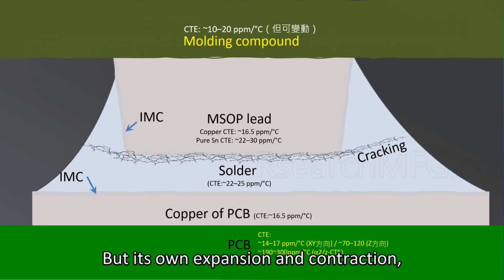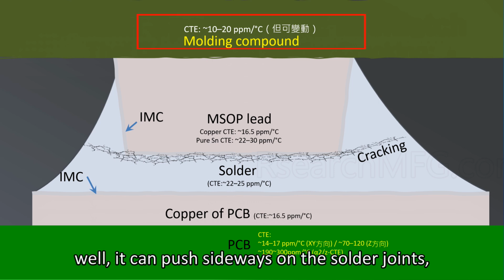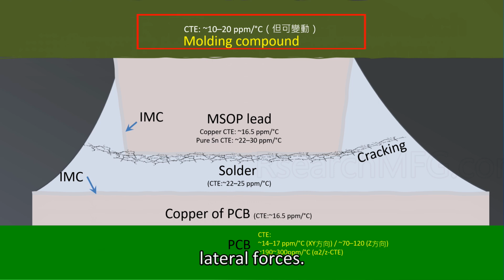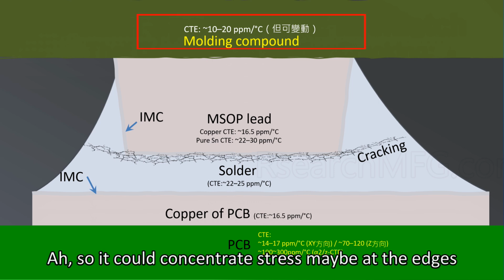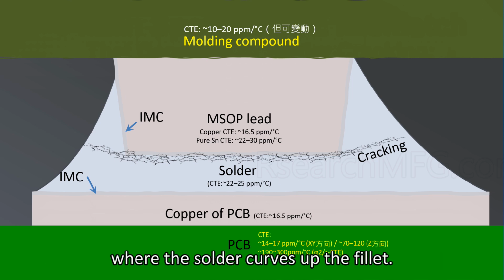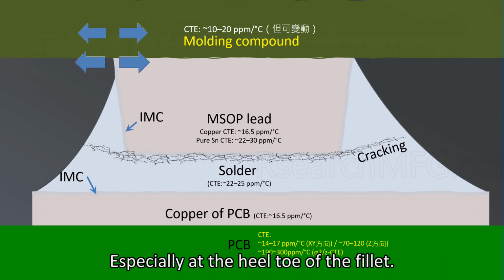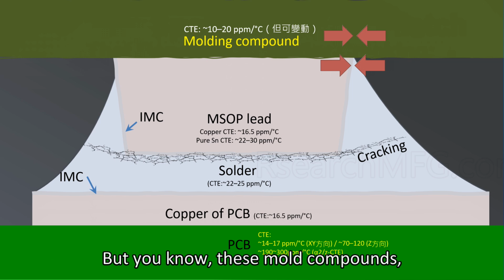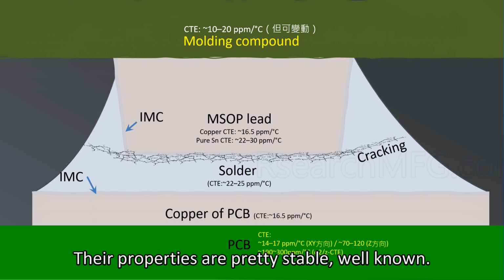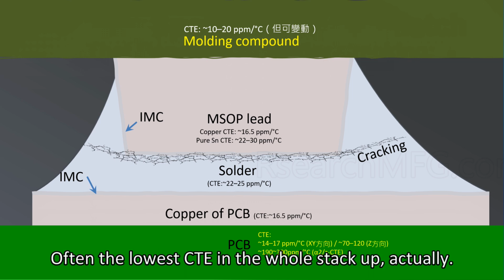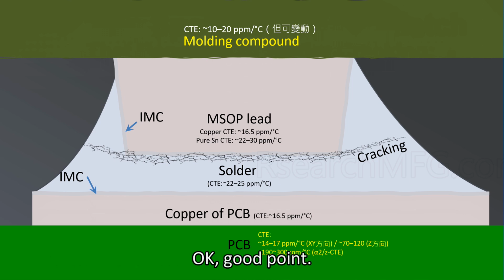But its own expansion and contraction, well, it can push sideways on the solder joints, lateral forces. So it could concentrate stress maybe at the edges where the solder curves up the fillet. Potentially, yeah. Especially at the heel or toe of the fillet. But these mold compounds, they've been used forever. Their properties are pretty stable, well known. Often the lowest CTE in the whole stack up, actually. Okay, good point.